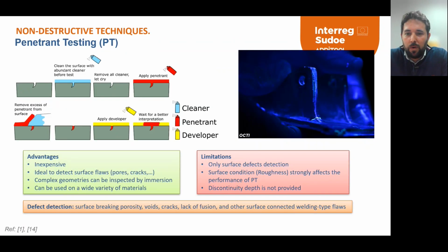Penetrant testing basically works by applying a penetrant agent onto the surface, and after removing the excess, a developer, typically a dry powder, is then applied to the surface to draw the penetrant out of the crack and produce a surface indication. This technique is only used to detect surface defects, but the main advantage is that it's inexpensive. On the other hand, surface condition affects the performance of the inspection, and also the discontinuity depth is not provided. You can see here, for example, an image with a typical indication of penetrant testing.